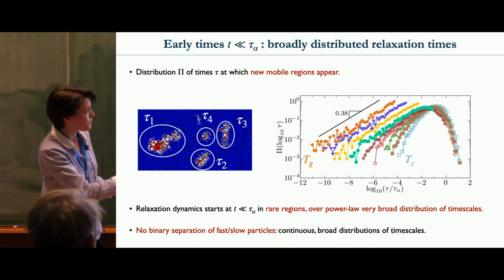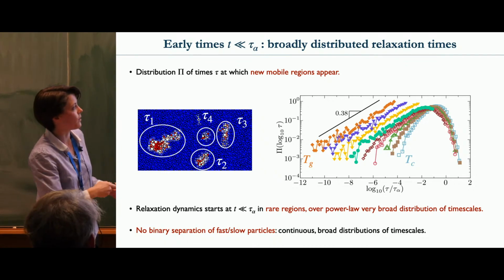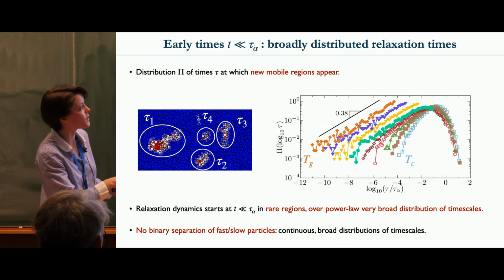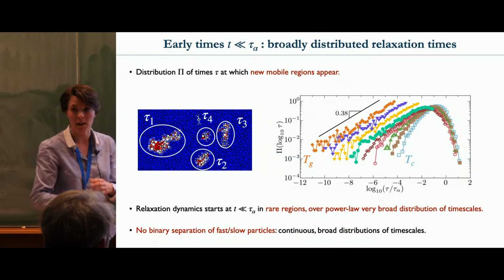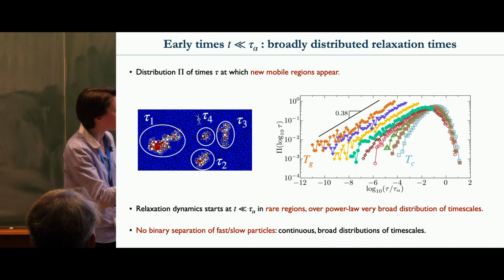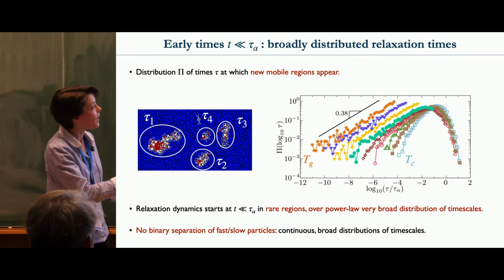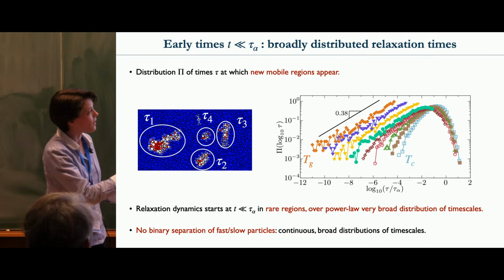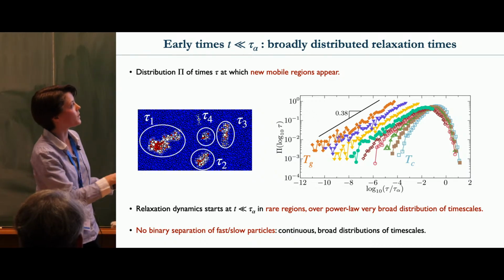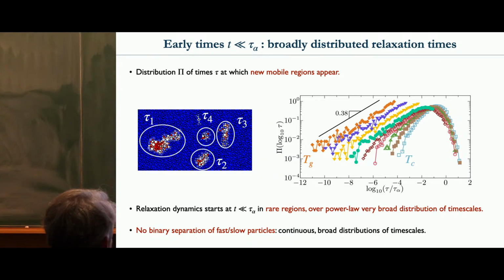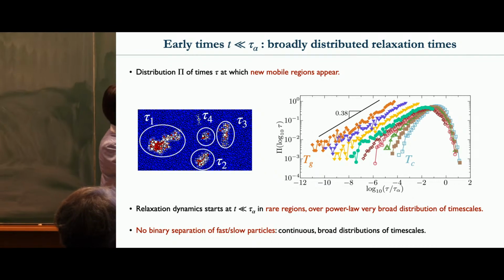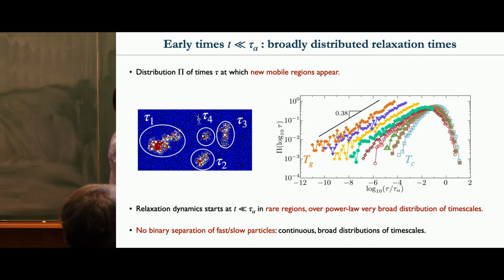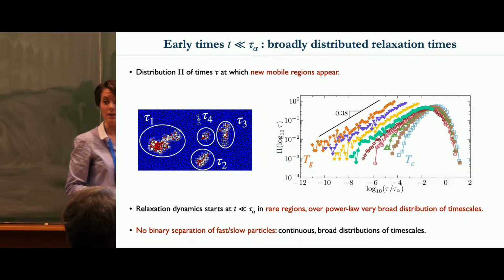In this curve, corresponding to the mode coupling crossover, you already have a broad distribution. Already 4 decades before the alpha relaxation time, you have clusters that start to appear. This is a continuous process. Eventually, at longer times, they merge, so this distribution goes down. As the temperature decreases, this distribution expands to lower and lower times, and eventually it covers many decades in time, and it follows a power law with a similar exponent to what I discussed before.